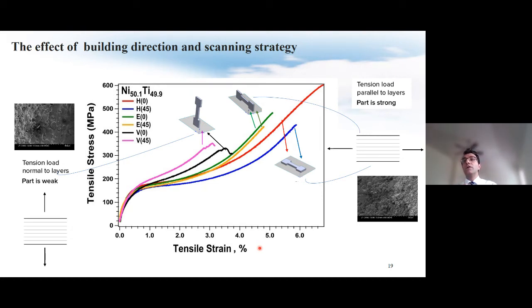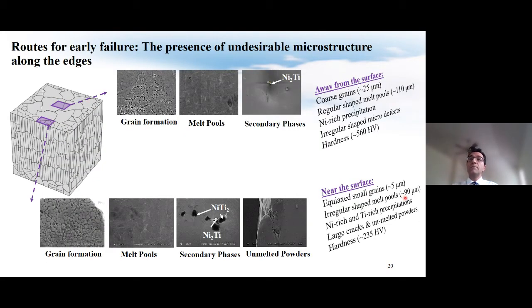By the way, although relatively higher strength was achieved, there was still room for improvement, and we decided to further investigate the microstructure and find other routes for early failure. Therefore, we decided to do a comprehensive study to evaluate the spatial microstructure properties of the SLM fabricated NiTi specimens. Before this study, all the available works in the literature were limited to local microstructure analysis rather than spatial one.